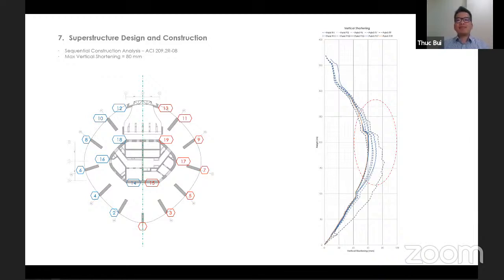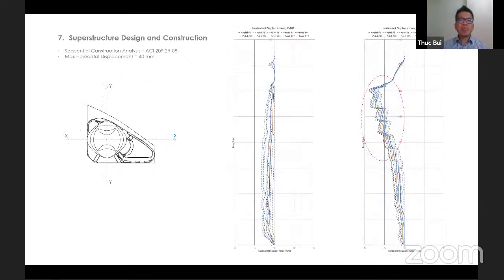We have also done the long-term vertical shortening analysis according to ACI 209, and the graph on the right shows the vertical shortening values for half of the podium on the floor plate. The maximum expected shortening is around 80 millimeters, and it's happening in this L-shaped column. Column number 1 also has shortening of around 70 millimeters. So in general, we provide compensation of 5 millimeters at every 5 floors.